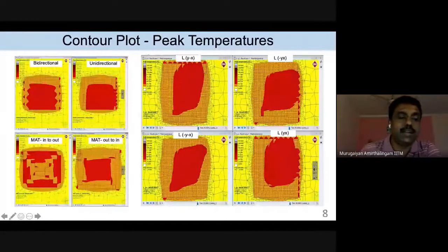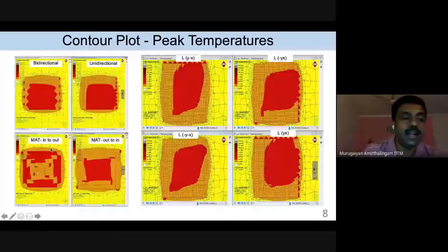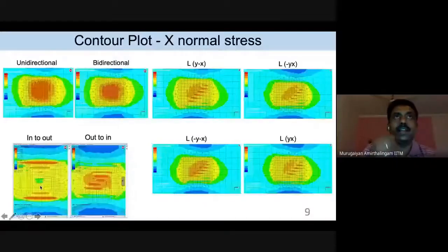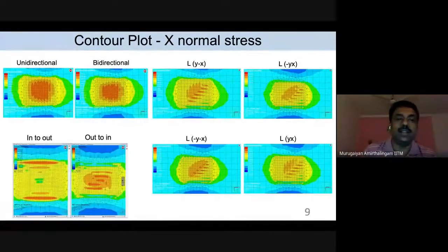So what are the paths we have to create, so that we can get a bead with minimal heat accumulation? You'll also see that the medial axis transformation provides the least residual stress and distortion inside the component. And this is possible only by doing all these mathematical simulations and understanding the metallurgy, solidification, and the influence of metallurgy on the residual stress evolution. Okay, so with that, I'll just end this talk.